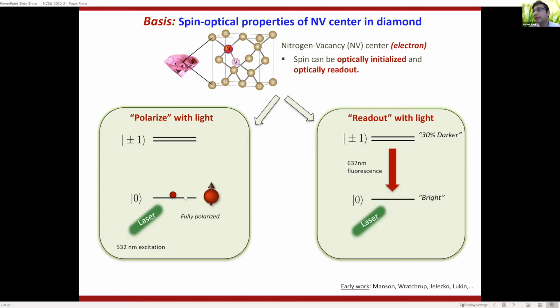And it turns out that these spins fluoresce very brightly in the red. And the two spin states here, so this is spin 1, so this is labeled ms equal to 0 and ms equal to plus minus 1. So these two spin states have a slightly different fluorescent contrast. So there is a spin-dependent fluorescent contrast. One state is bright and one state is dark. I mean, it's not completely dark, it's slightly darker. And you can tell if a spin is up or down based on the fluorescence that you collect from the spin.